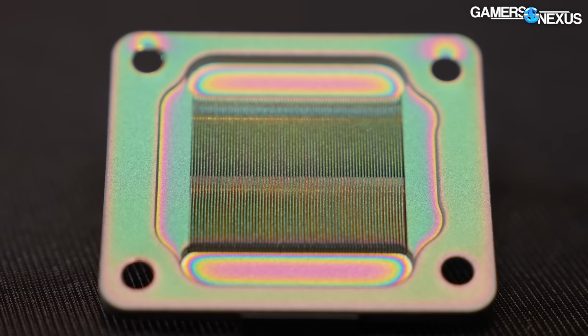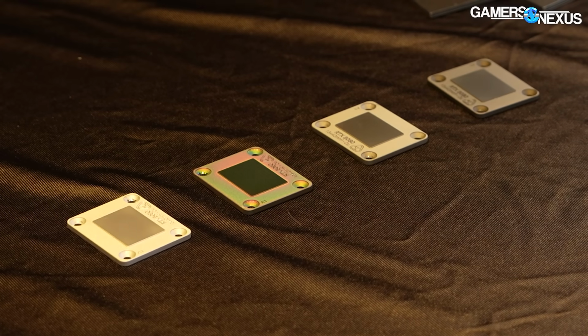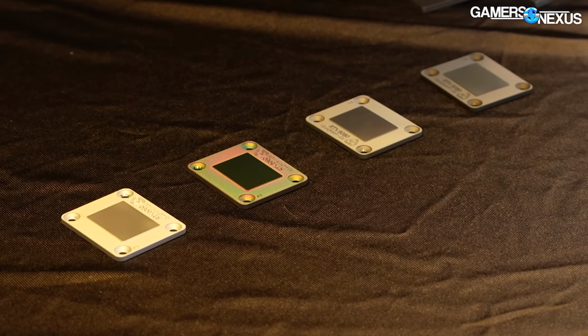And then on the other side you have what they call the target. It might sound a bit weird because you might think this is the target. Right, yeah. But the target is the metal base you're starting with, and that's getting hit by what you could call lightning. And the lightning is then releasing metal ions, and they will stick to the surface. You can have multiple different metal sources or targets, and then you can have process gas in between. And then you can come up with a lot of different coatings.